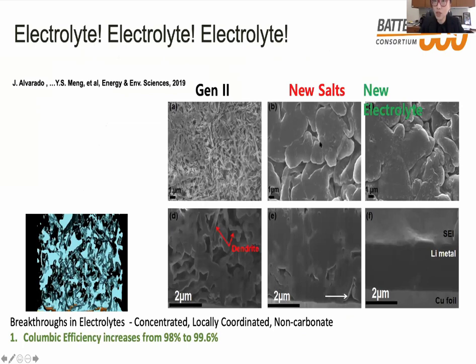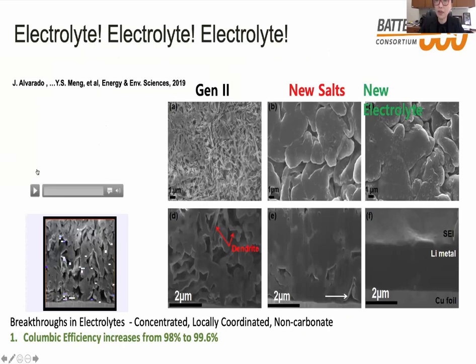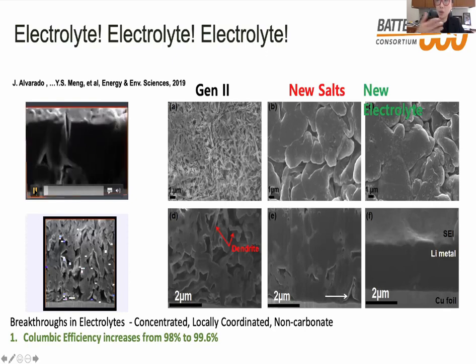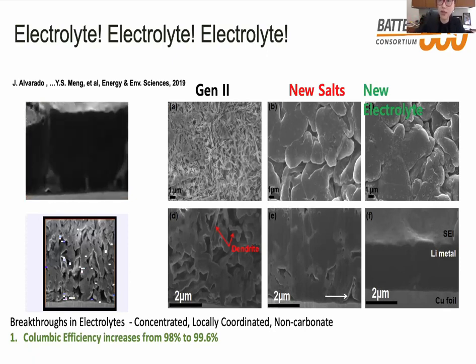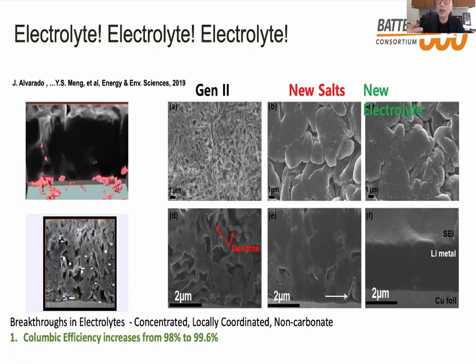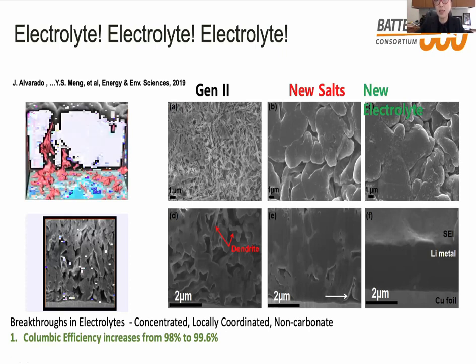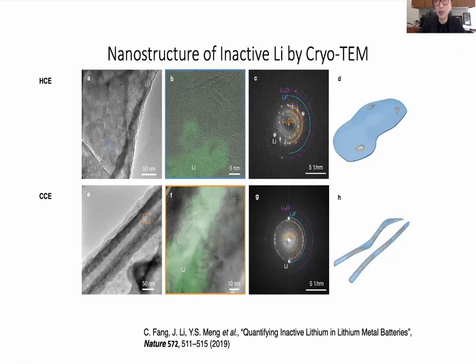And when we actually change the solvent and the salt, now we have a very effective tool. You can actually look at the three-dimensional tomography of the lithium deposit. Obviously, when you change the solvent and the salt, the crystal size and everything of the lithium is very different, right? So this gives us a way to properly measure, if you did modify this electrolyte, if you did modify things, where is the actual phenomena you see.